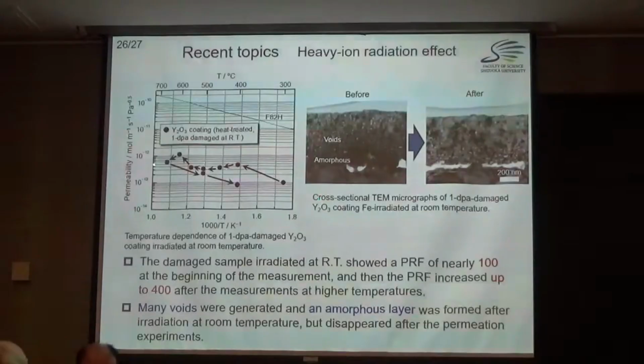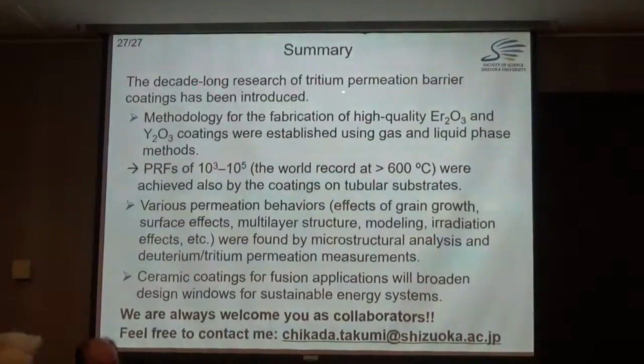In the case of the yttrium oxide coating, the irradiation makes an amorphous structure and many voids in the coating. After permeation measurement, where the temperature increased up to 700 degrees C, the amorphous phase was crystallized and the voids disappeared by recovery of the damage. Then the PRF is about 100 to 400 before and after permeation measurements. We are now dedicating our effort to clarify how the amorphous structure affects the permeation property. This is a summary of my talk.